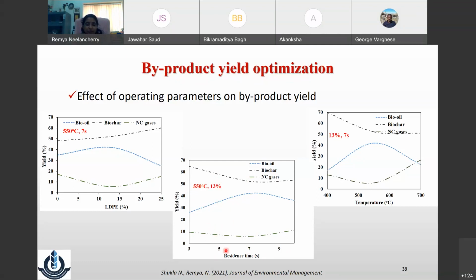So we can think of optimizing or keeping a particular value of each of these parameters based on the type of end product you are targeting. And the same is the case with temperature. The lower the temperature, you can get more biochar. But if you increase the temperature, say 500 to 600 degrees Celsius, the bio oil component will be more. If you further increase, most of them will get volatilized by secondary cracking, and you can get the biogas as the major end product. Again, it is up to you to tune which byproducts you are aiming at.